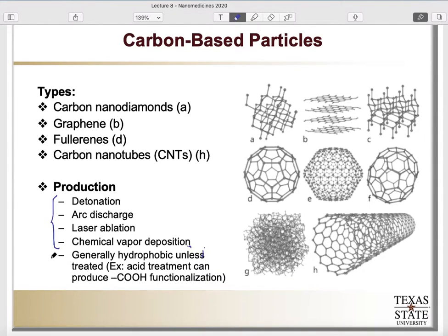Now, one thing that I have here that is not really in terms of production, but more of the modification that typically is done for the use of these carbon-based materials in biomedical applications is the fact that because they're carbon-based, carbon only really, they tend to be very, very hydrophobic. And so the applications can be minimal in biomedicine unless they are modified. And typically the treatment is exposure to strong acids. That acid treatment can actually provide carboxylic acid functionality to many parts of the macromolecule, and that provides it with water solubility.